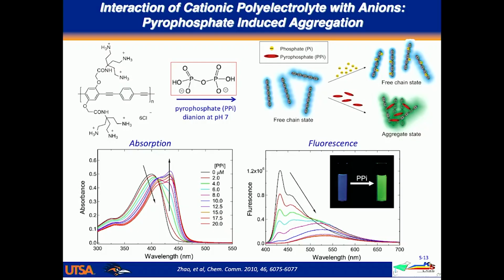It turns out, as I'm going to show you, the aggregation is also reversible. So if you remove pyrophosphate from the solution, you can recover the molecularly dissolved polyelectrolyte. It turns out this effect takes place at relatively low pyrophosphate concentration. And so, as shown here, it can be a useful sensor for just the presence of pyrophosphate in a solution. But as I'm going to show you a little bit later, we can also couple this with enzymes and use it as an enzyme biosensor.